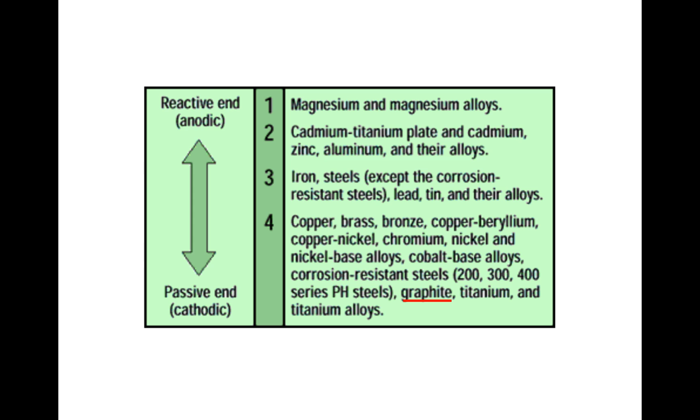Now instead of using aluminum nipples, if we use brass, we would be down here in the same activity category as graphite. So we wouldn't have a problem with brass nipples, but heaven forbid that we do that, because they are slightly heavier, and that is a perception problem at least.